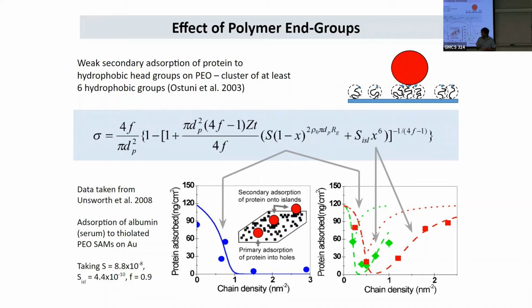Right, and interestingly, none of that matters, right? So yes, these are different proteins, and if they say they're using albumin, we actually go in and take the size of albumin, and that's enough. That's all we need to know about the protein: what is the size of this protein? In fact, the shape changes too. When you say instead of albumin, I'm using fibrinogen or fibronectin or whatever, that's not even a spherical protein, it's a cylindrical protein. And so those geometries matter.